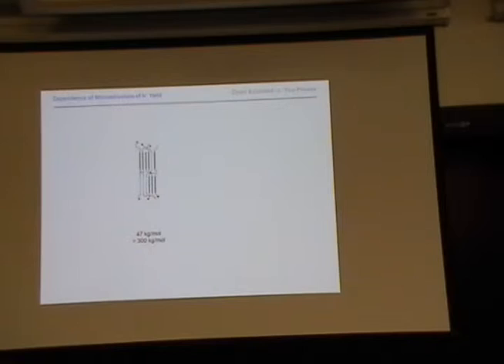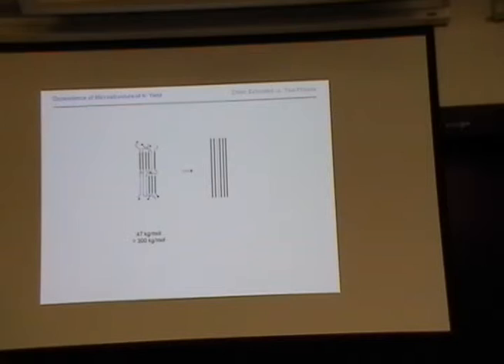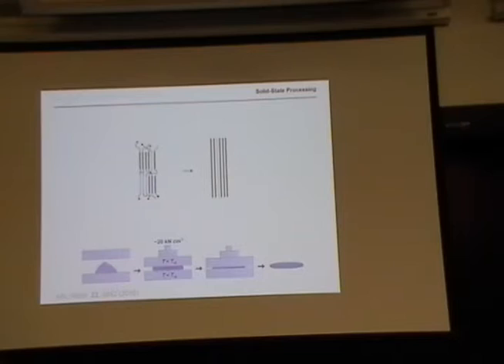Now processing comes into play — and that's actually what I like to do. We took two materials, both of them having entanglements: a 50 kg/mol material which we believe has two or three entanglements, and one of high molecular weight where we really know it has many entanglements. We simply wanted to take this material and make chain-extended crystals with it. How can we do that? Very simple.